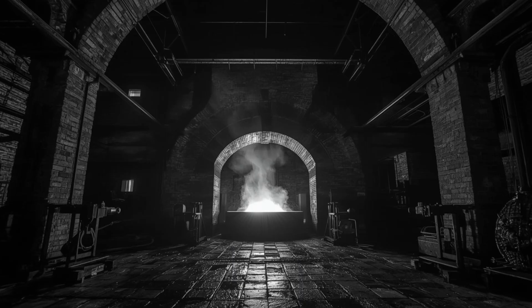He pointed to the cross-section drawing showing the furnace wall composition. "Your refractory lining consists of firebrick, highly porous, with significant air content. This porosity gives it excellent insulation properties, but also means it contains thousands of small voids. When this brick is heated to 2200 degrees for months, several things happen. First, any residual moisture in the brick and mortar is driven deep into the wall structure. It doesn't escape, it migrates inward away from the heat, condensing in the cooler layers behind."